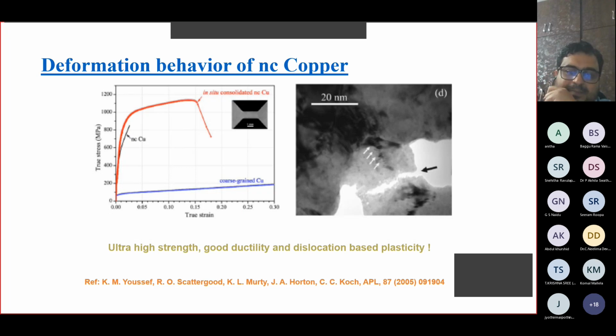And in this paper, which was published in Applied Physics Letters way back in 2005 from the lab where I did my PhD, it shows that there is some kind of dislocation activity in a copper grain whose grain size is about 20 nanometers. And also because of dislocations, we have high strength and reasonable amounts of strain hardening. And these materials are defect free. There are no other defects except the lattice defects that we have. So therefore, the realization of ultra high strength, good ductility, and dislocation based plasticity can be seen. And at the time, and still I think, this is the best copper that is available in the market, which is really strong and reasonably ductile.